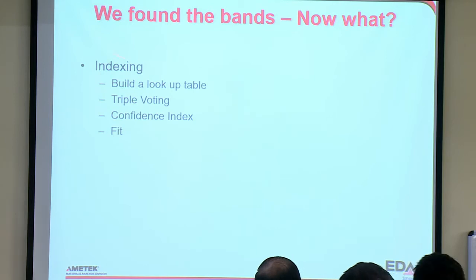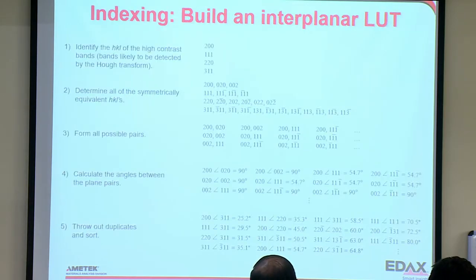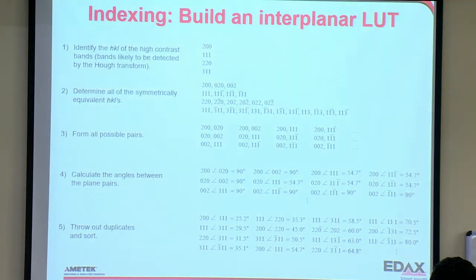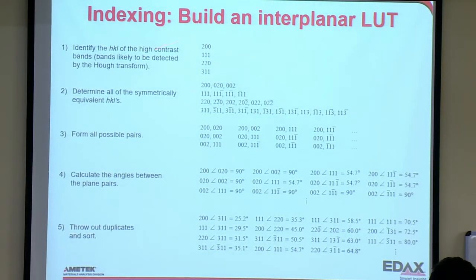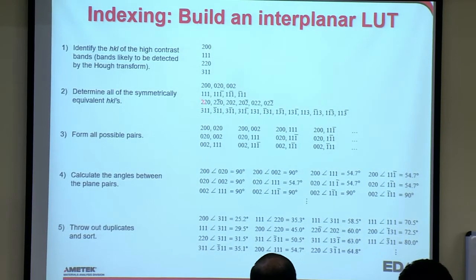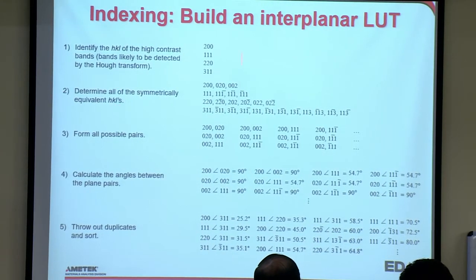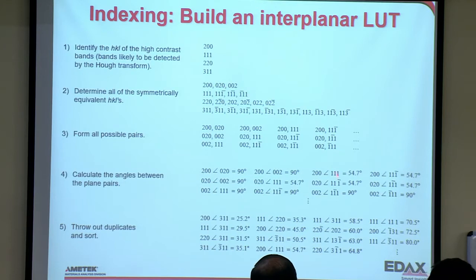So we use the transform to find the bands. Now what do we do? This step we call indexing. The first step is to build a lookup table of interplanar angles. We know which planes in our crystal are likely to produce bands, and we need to identify those. In this case, it's this set here for an FCC material. We determine all the symmetrically equivalent versions of those, form all possible pairs, and calculate the angles between them.